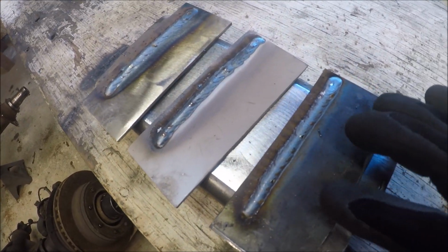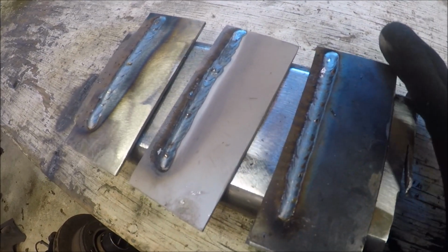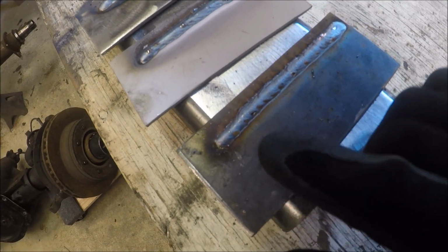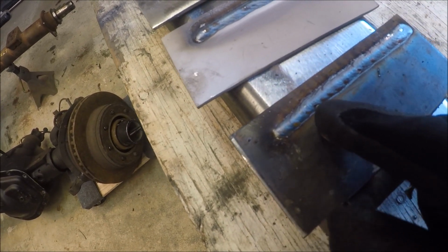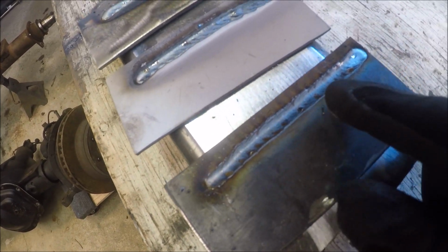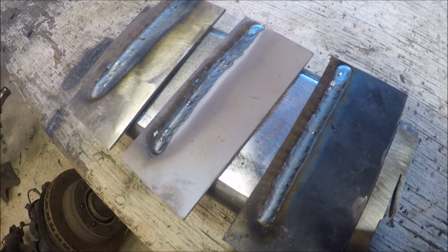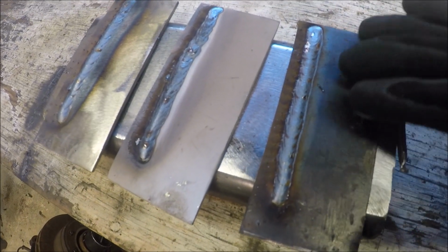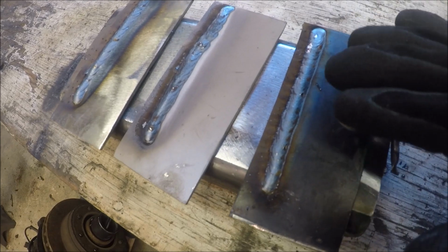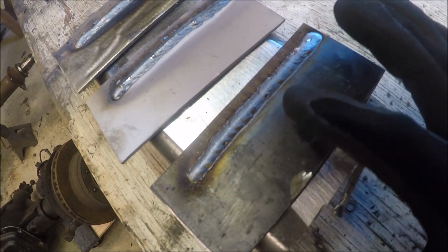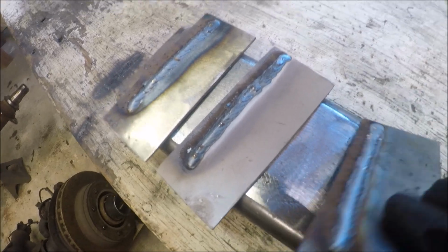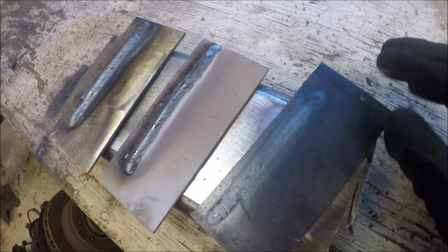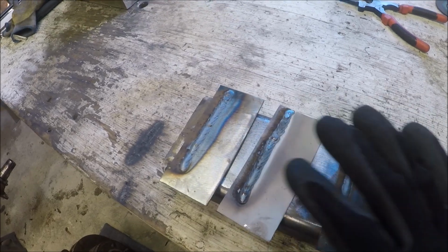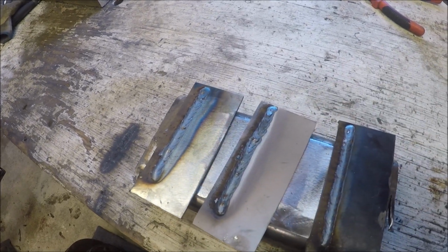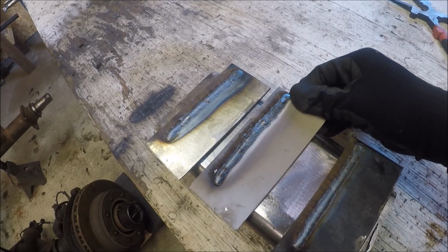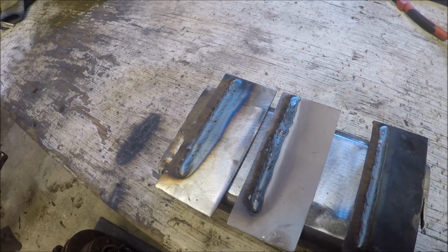And then this is the dirty steel, or at least still has mill scale, a little bit of rust, and actually this turned out pretty good. There's definitely some little pockets of porosity in it for sure, and that's because I'm sure there was some contamination in the weld, but overall that one actually turned out pretty well. Pretty good as well. It is a little bit more built up than the other ones, almost like it was colder, but still I got some good heat penetration. So I'd actually like to throw down one more pass here and see what the results are again, and then we might try this out on a little bit thicker steel to see if we're still getting good heat penetration.